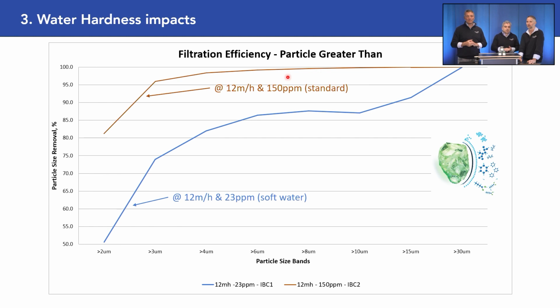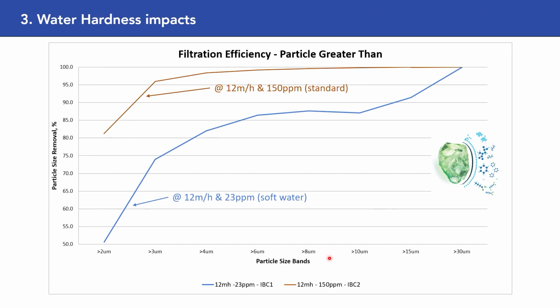And we compare this chart with the one with really soft water at 23 ppm. That would be 2.2 French degrees, 1 German degree. So there is a big impact on the filtering performance depending on the hardness of the water. And again, this is done with AFM-NG. If you would see this with AFM standard or with any sand or glass media, the blue line would just collapse down to 10 micron, if not lower. So really the NG is the only media which can handle soft water pretty well without any addition.